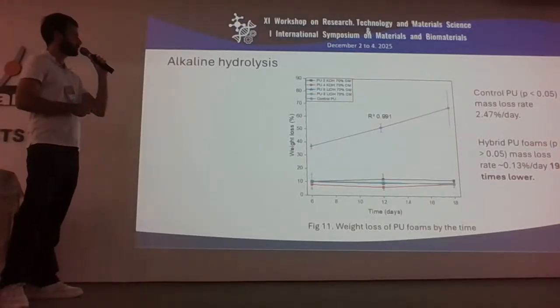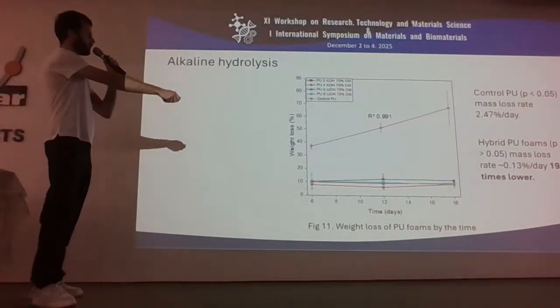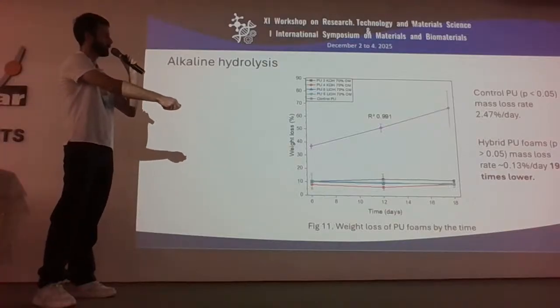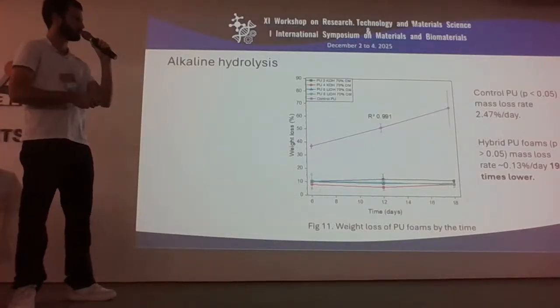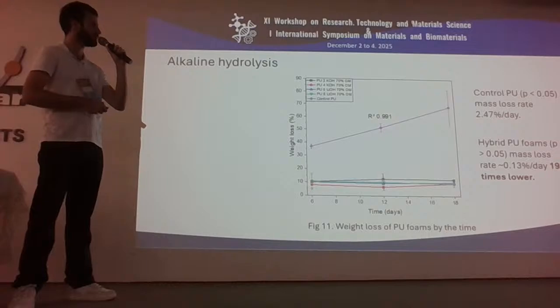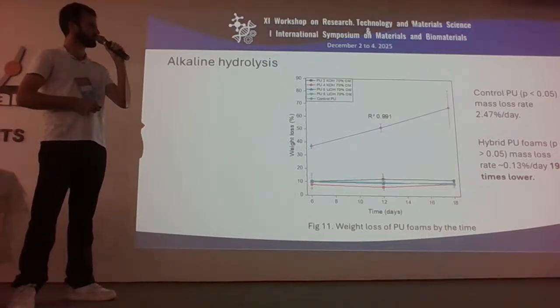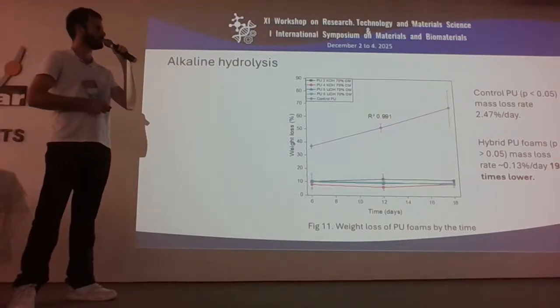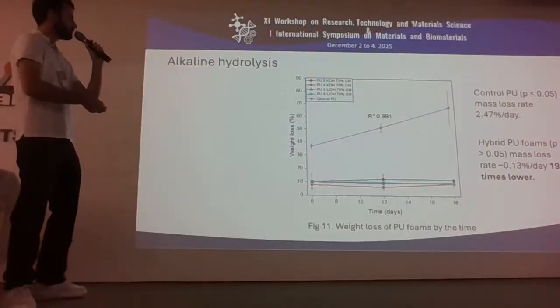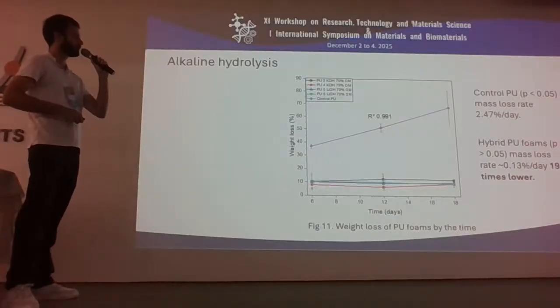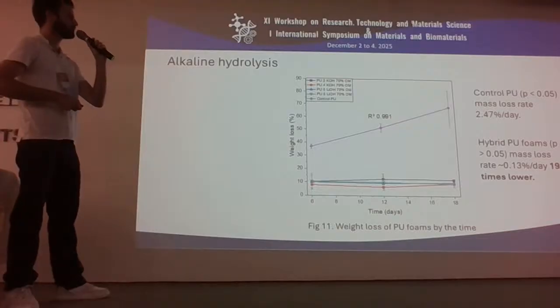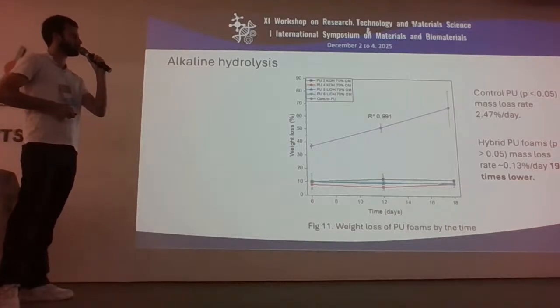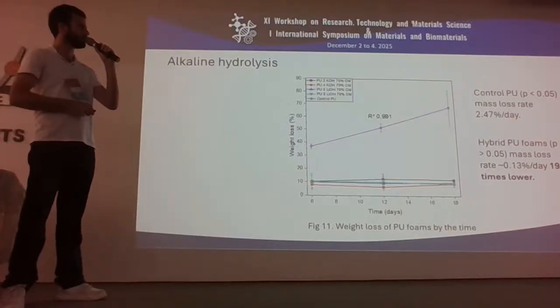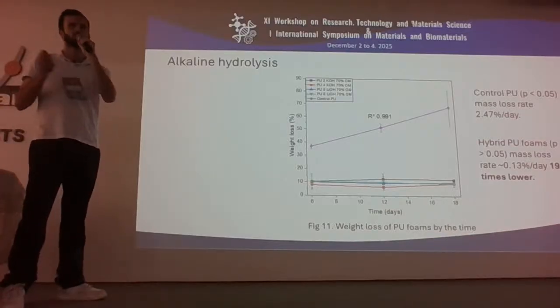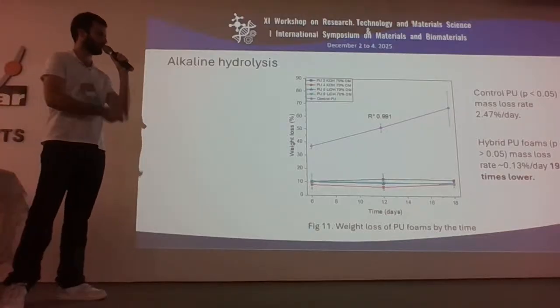And for the alkaline hydrolysis tests, we can see that the castor oil foam showed a linear degradation with a mass loss rate of 2.4% per day. It showed a weight loss around 70%, and it was statistically significant. But with the addition of 30% of oxypropylated polyol, the hybrid foams showed a mass loss rate around 0.13%, being 19 times lower than the control foam, and they were not statistically significant. So only the castor oil foams really degraded.